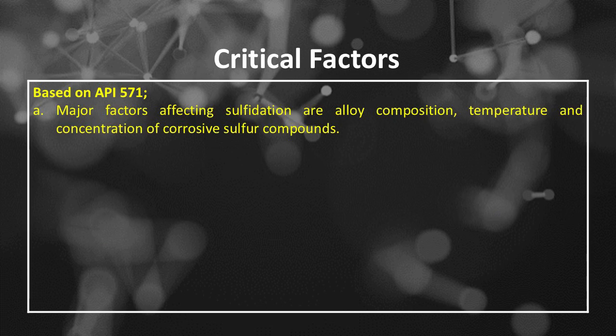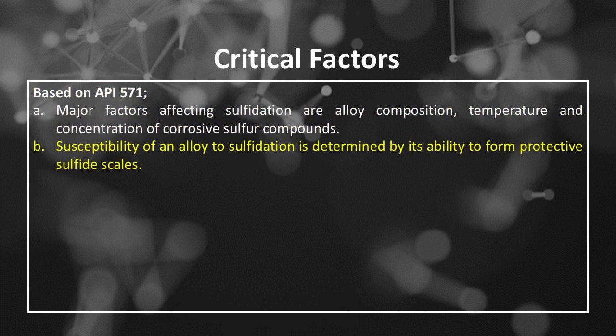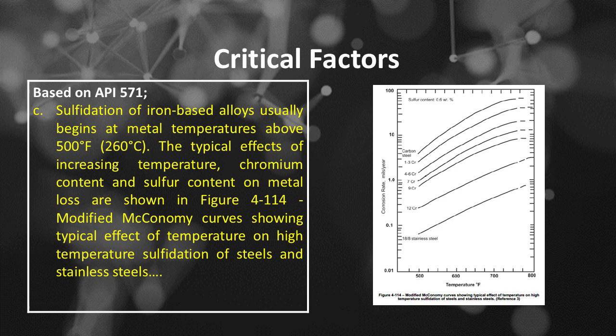Sulfidation corrosion damage mechanisms. Critical factors based on API 571. Number A, major factors affecting sulfidation are alloy composition, temperature, and concentration of corrosive sulfur compounds. Number B, susceptibility of an alloy to sulfidation is determined by its ability to form protective sulfide scales. Number C, sulfidation of iron-based alloys usually begins at metal temperatures above 500 degrees Fahrenheit or 260 degrees Celsius.